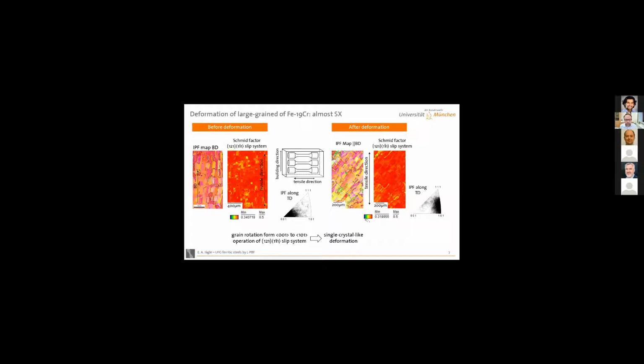Right, before I dive in, just to show you what these alloys look like, or this particular alloy, iron chromium, what this looks like if you deform it, if you process it without any additional nitrogen or what have you. The texture is very, very strong. It's not really single crystalline, of course, but essentially it behaves like a single crystal because it's a very strong texture.